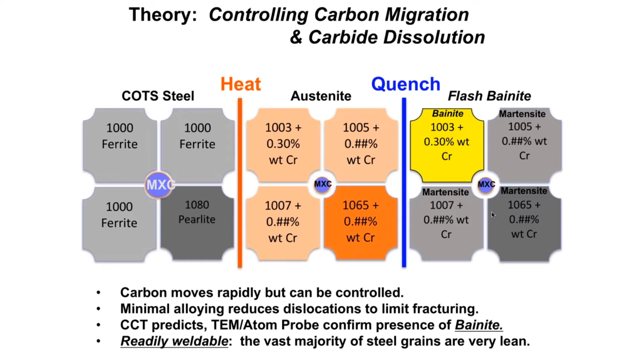Now, we very rapidly quench this. So this is a process where you heat up in a few seconds, you quench a few seconds later, and we end up getting some results we expect in our flash bainite process. In the lower right corner, you can see martensite, 1065 plus some percentage of chromium. Of course, that's a higher carbon martensite. The 1005 and the 1007, as expected, that is lath martensite. What's interesting is in the yellow box, the 1003 plus 0.3 chromium actually forms bainite.